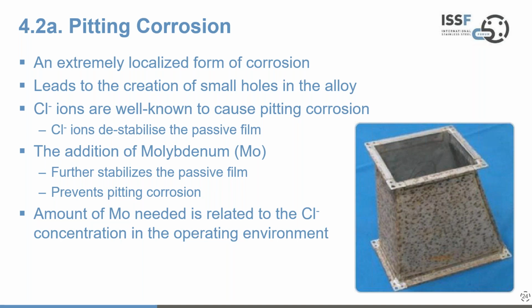Now I'd like to move on to the second of our corrosion mechanisms, pitting corrosion. This is described as a localized form of corrosion. It leads to the creation of small holes in the alloy as depicted in the photograph on the right. And chloride ions are really well known to cause this type of corrosion because fundamentally they destabilize the passive film. But you can overcome that. The addition of molybdenum restabilizes the passive film and prevents that pitting corrosion.